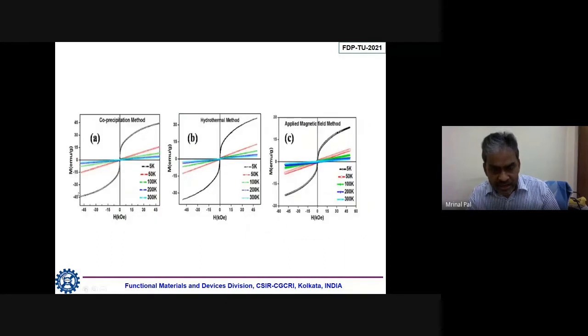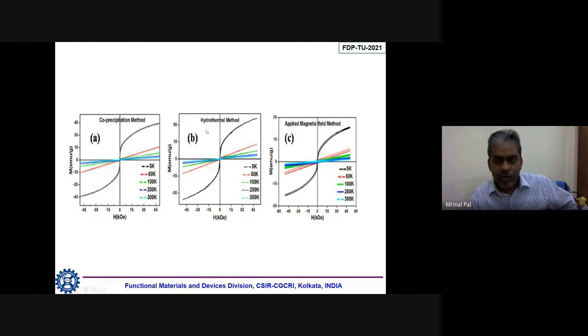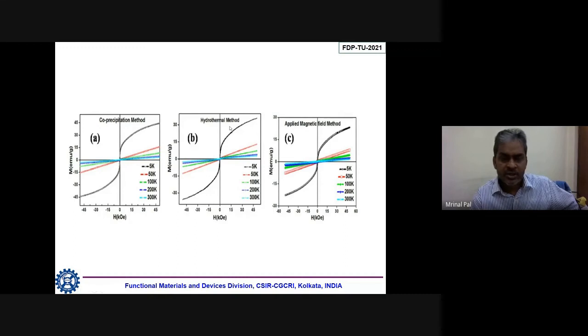And the most interesting thing is that because of this different morphology or different structure of the cobalt nanoparticle, we are able to create different magnetic properties. You can see the graph, their magnetic moment. This is a hysteresis loop at different temperatures, starting from low temperature 5K to 300K. But you see that the saturation magnetic moment value is very much different. In this case, it is almost 45 emu per gram. In this case, this is when we prepared it by hydrothermal process. This is around 30. And when we applied some magnetic field to prepare this nanorod, in that case, the magnetic moment is a little less.